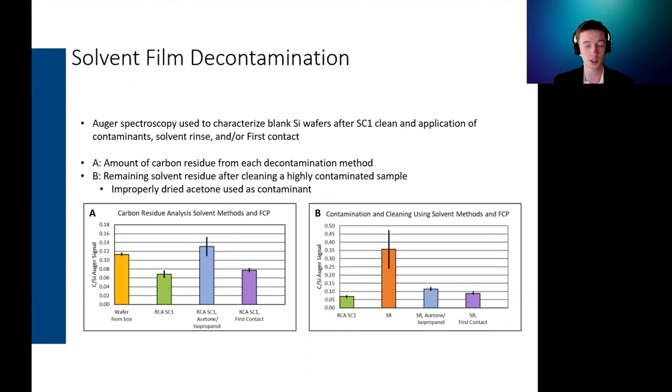From that we cleaned those samples using First Contact and also our solvent methods, which is an acetone isopropanol rinse. Both of those methods brought it back down to around the area of a fresh wafer, though First Contact was marginally better. Next slide please.